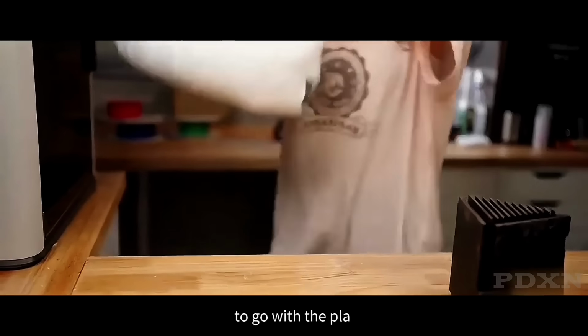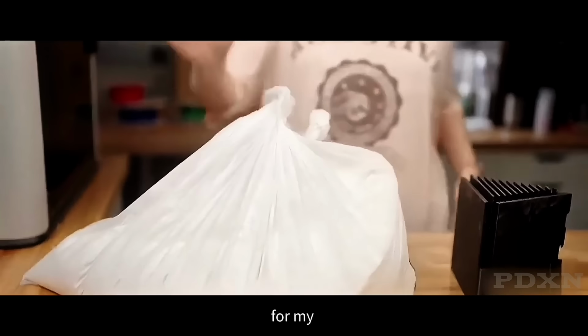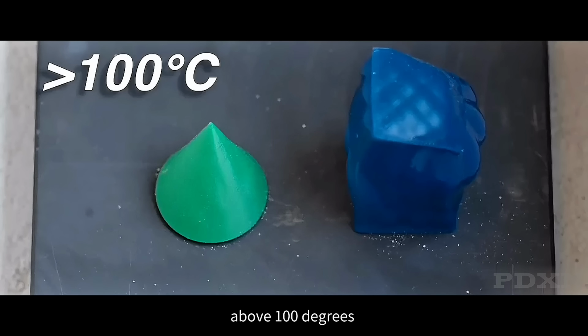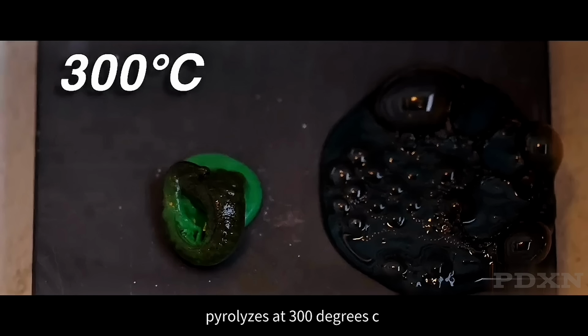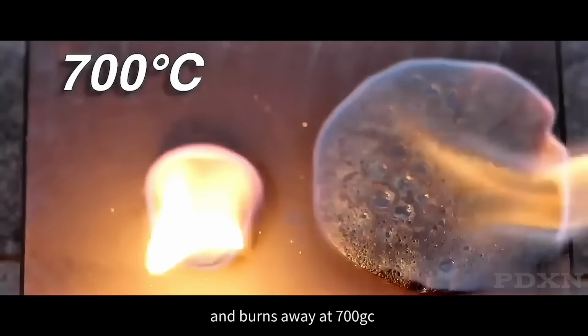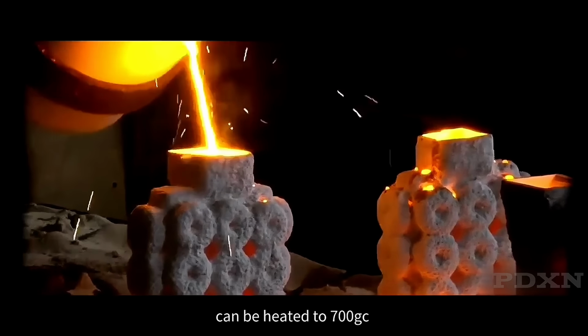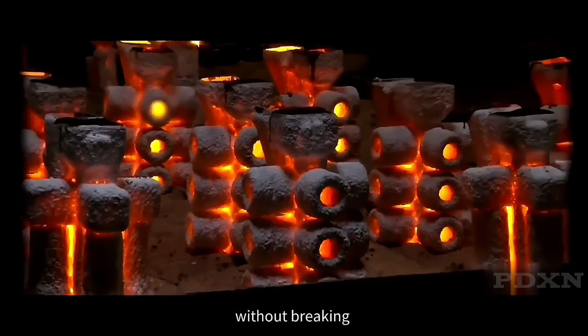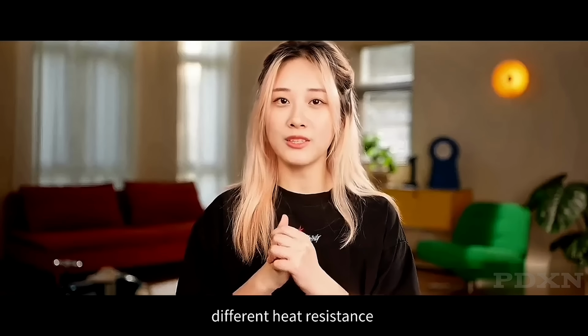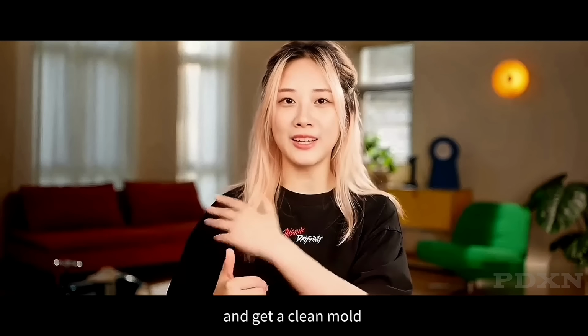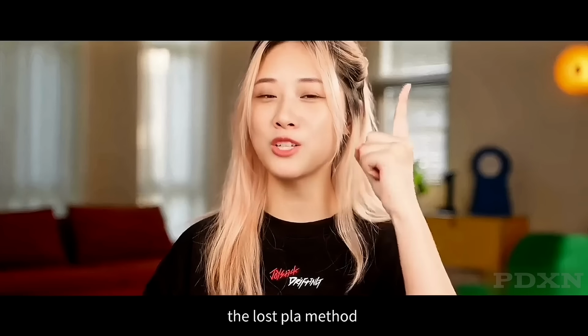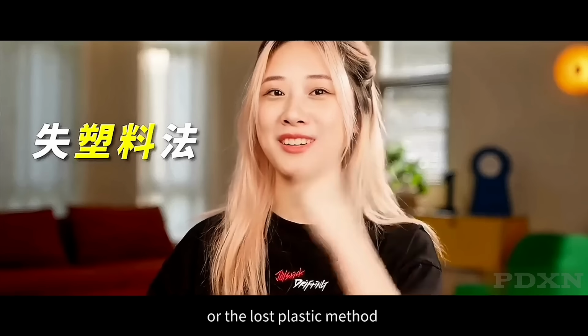To go with the PLA, I picked a high temperature plaster for my mold. PLA melts above 100 degrees C, pyrolyzes at 300 degrees C, and burns away at 700 degrees C. The high temp plaster can be heated to 700 degrees C without breaking. By using their different heat resistance, I can remove the PLA and get a clean mold. This method is called the lost PLA method or the lost plastic method.